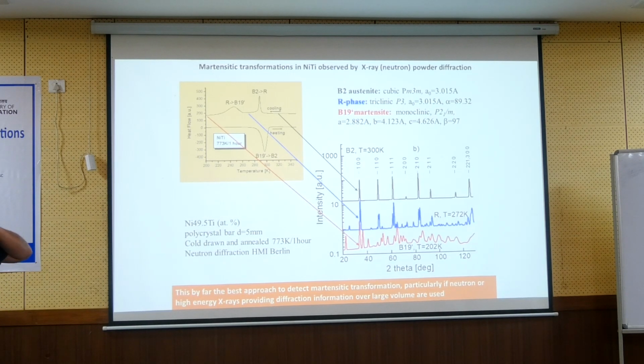Of course, there are two ways. The lab X-rays take information only from the surface of the specimen, so you have to be sure that the surface is the same as your bulk. So carefully polish. In addition, I myself did a lot of neutron and synchrotron X-ray. In that case, the information is taken from the whole volume, so you don't have to care much about the surface. And also, if you do in situ loading, you get the average information over all volume,